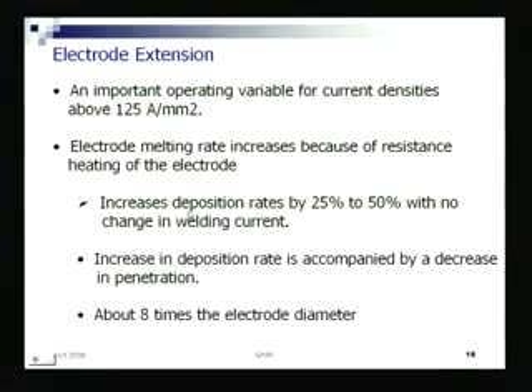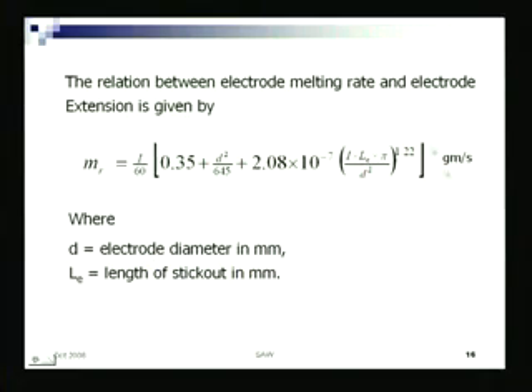The electrode is getting heated up, so it will not come straight, it will get unstable. Again, it does not mean that the deposition rate will go on increasing with increasing electrode length. Up to a certain point it will work, then the whole process will become unstable. There are some empirical relations through which one can find out approximately how much would be the electrode melting rate for a given electrode extension, and how the electrode extension is changing.